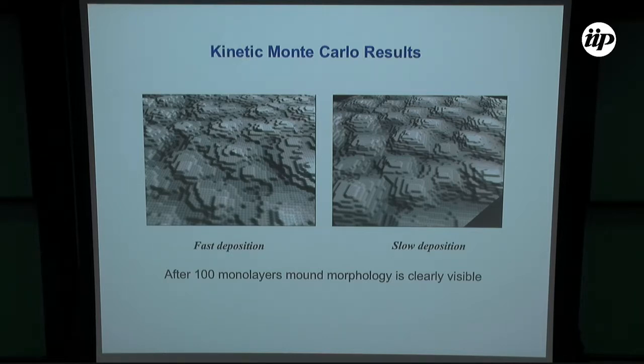structure. And when you introduce the barrier, instead of finding the result that I showed you before, namely a self-affine fractal, what you find are actually these mounds. So mounds do appear once you introduce the step barrier in the Monte Carlo simulation. We did a variety of simulations with different parameters, as well as the speed of deposition, which you can also think about as the temperature of the substrate. High temperature substrate or low temperature substrate produces the same effect as fast deposition, slow deposition. And in all cases, what you observe is the formation of these islands or these mounds. This is after just 100 layers.